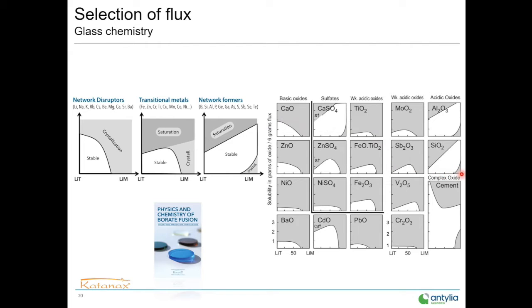If you use pure lithium metaborate on this side, you can digest up to 1, 2, 3, 4 and more grams of silica in 6 grams of flux. So the difference is very huge. You have examples here of other elements, combined elements. You can see calcium alone versus calcium sulfate, the gypsum sample, there's a huge difference in solubility behavior.